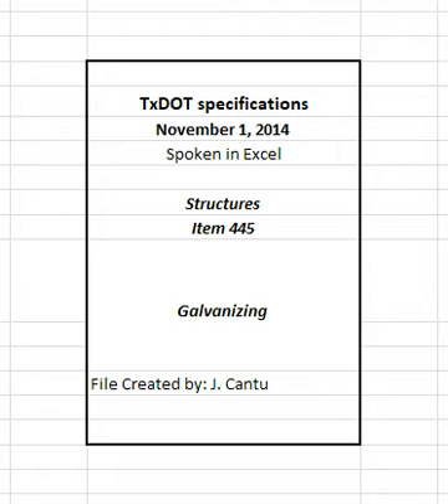3.5.2.2 Sprayed zinc, metallizing. Remove oil, grease, corrosion products, and any welding slag or flux from surfaces to be repaired, and ensure the surfaces are dry. Clean surface to white metal by wire brushing, light grinding, or mild blasting extending into the surrounding undamaged galvanized coating. Apply coating by metal spraying pistols fed with either zinc wire, ribbon, or powder. Provide a coating that is uniform and free of lumps, coarse areas, or loose particles.